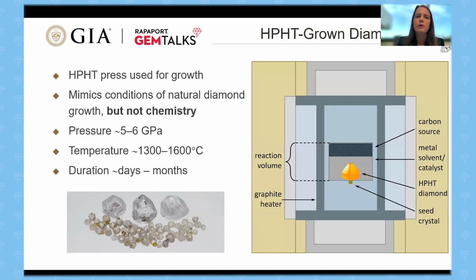So the HPHT grown diamonds use an HPHT press. Again, HPHT stands for high pressure, high temperature. And it's going to mimic some of the key conditions of natural diamond growth, but not the chemistry.